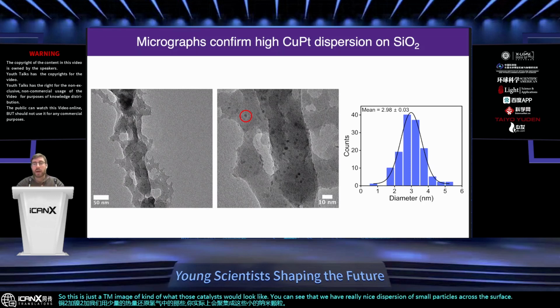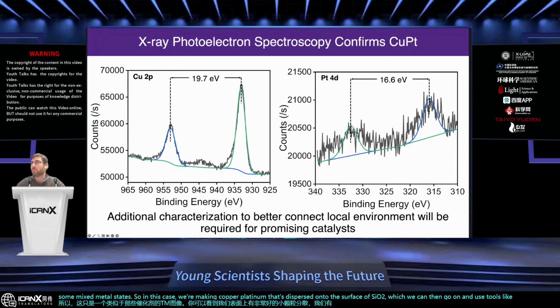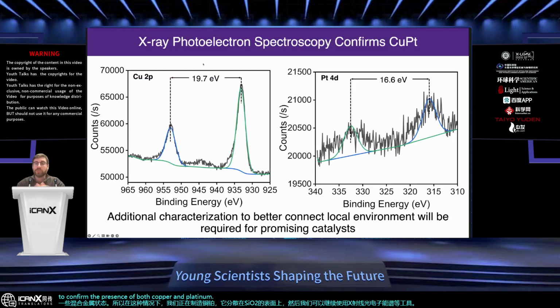So in this case, we're making copper platinum that's dispersed onto the surface of SiO2, which we can then go on and use tools like X-ray photoelectron spectroscopy to confirm the presence of both copper and platinum in the system. And of course, there's many, many other characterization tools that will be needed to really understand the local bonding environments and the dynamics of these systems overall.